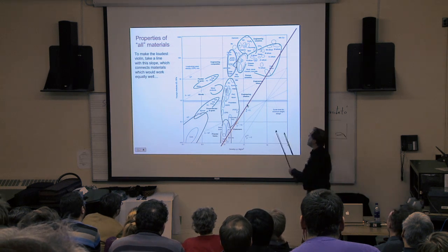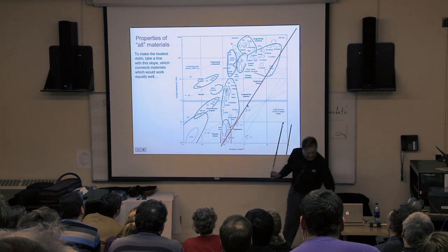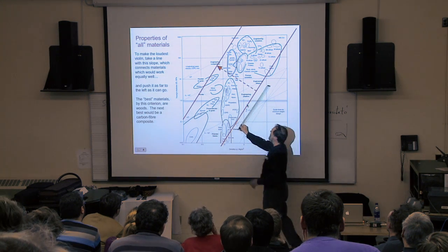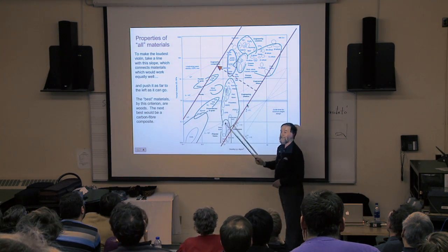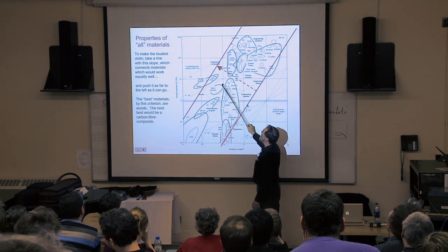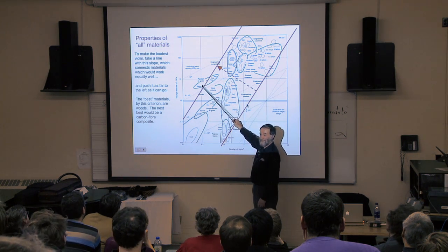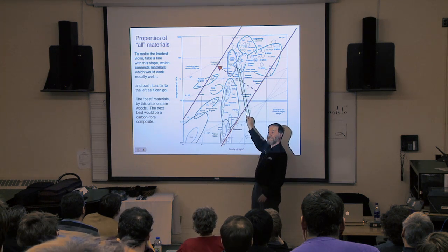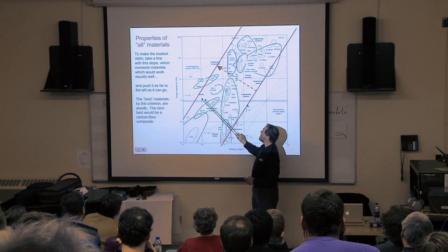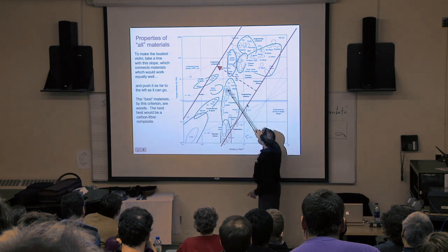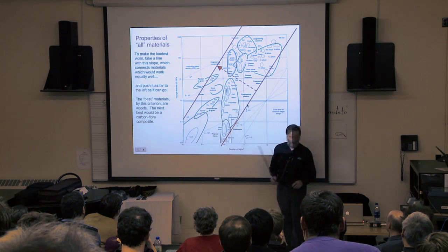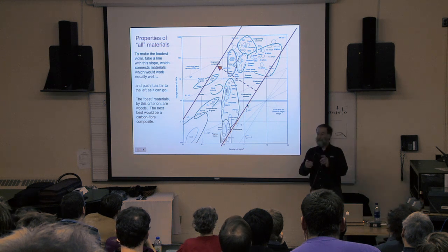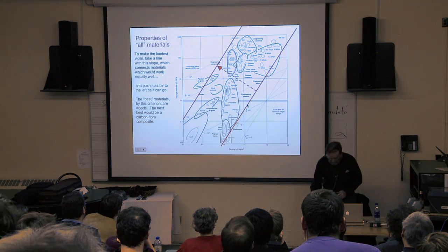We want to make things louder. We have to take this line and roll it across the diagram and push it as far that way as we can go. And what is the very last material we come to? We push these lines over to here. It's over here in the wood island. It outperforms every other easy material. Not quite true, but nearly. So wood is not such a silly material for this particular business of making mechanical amplifiers that are loud. Wood is quite a good idea.